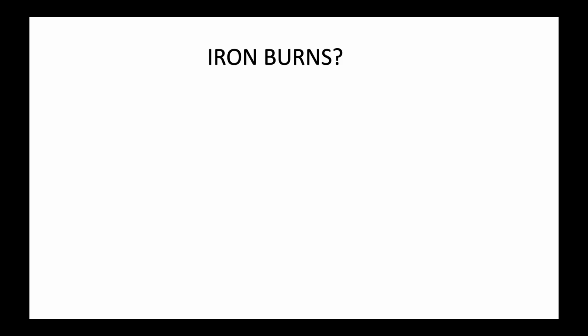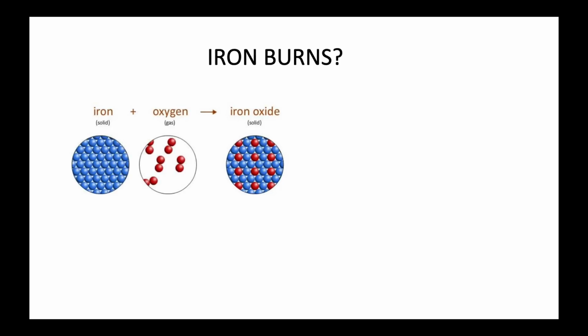If you burn a piece of iron completely, it releases 10 times the amount of energy needed to melt that piece of iron. So the sparks you see are iron burning, melting itself and mixing in some iron oxide to make these iron-rich spheres. When iron burns, it gets so hot it melts the adjacent iron and it mixes in with the molten iron and the iron oxide, and it makes these tiny little spheres.